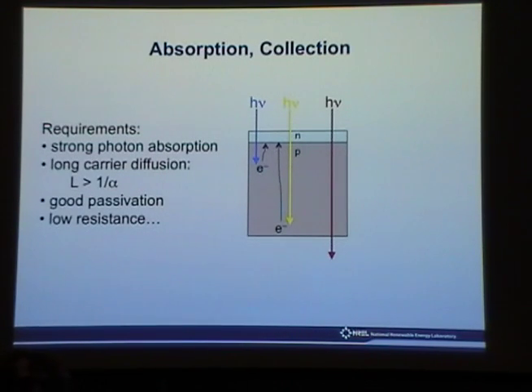Gallium indium phosphide has a slightly different absorption coefficient. An optically thick gallium indium phosphide cell is about 3 microns. So if you put gallium indium phosphide on top of gallium arsenide, you'll get some current in the gallium indium phosphide, you'll get some current in the gallium arsenide. They're probably not going to be the same. So if you thin the gallium indium phosphide, you're going to sacrifice some of the current in the gallium indium phosphide. In other words, you're making it thinner than its absorption thickness, and so some of the light is not going to be absorbed. And so in that way, what you would do is you would lower the current in the gallium indium phosphide cell, raise the current in the gallium arsenide cell, and you can current match.